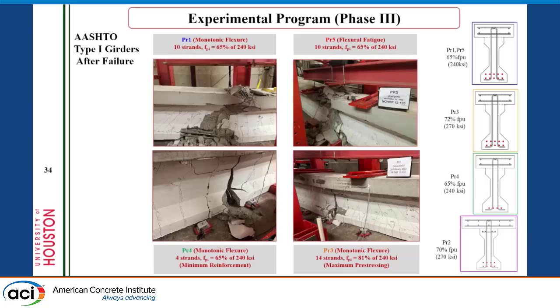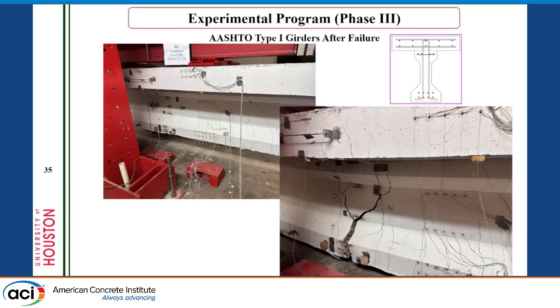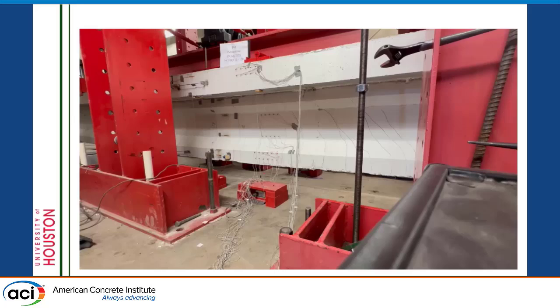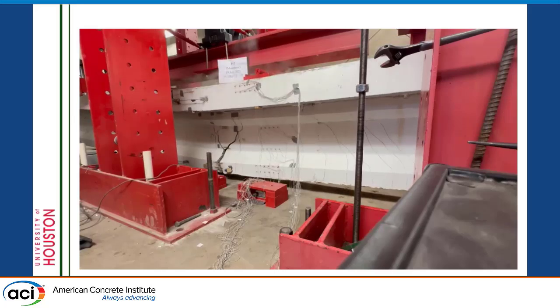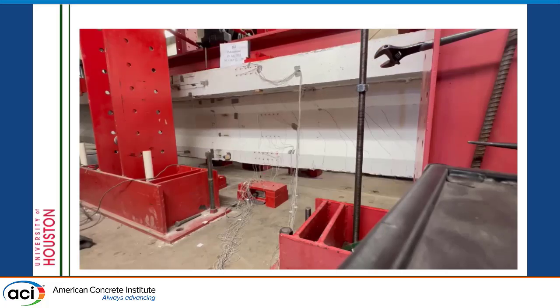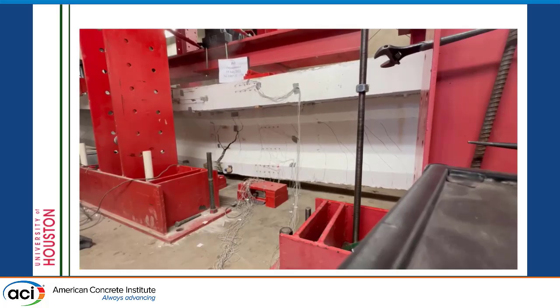What we noticed when we have this strand rupture is a big crack in the middle. But this big crack doesn't reflect what's going on in the post-tension, because in the post-tension it's a different story: it's debonding, it's concentration of the stresses, and that appears from the very beginning, but this one appears only at the failure. This is our test, and you can see exactly when the crack appears. It wasn't before, it's just at the level of the rupture that the crack appears. So it has nothing to do with debonding when we talk about the post-tensioning. That's the strand rupture.